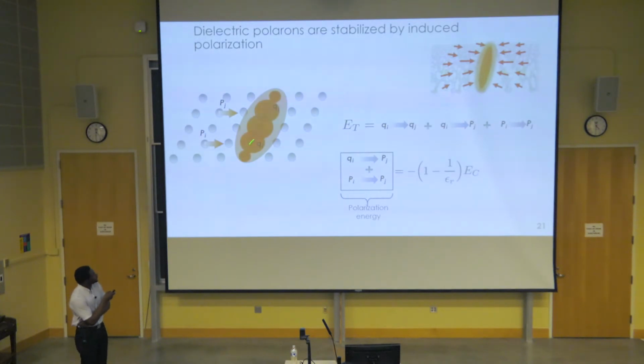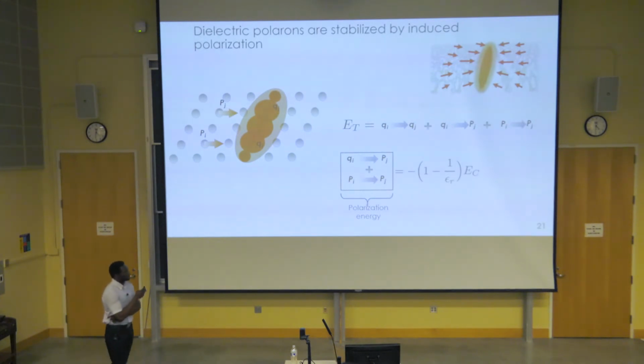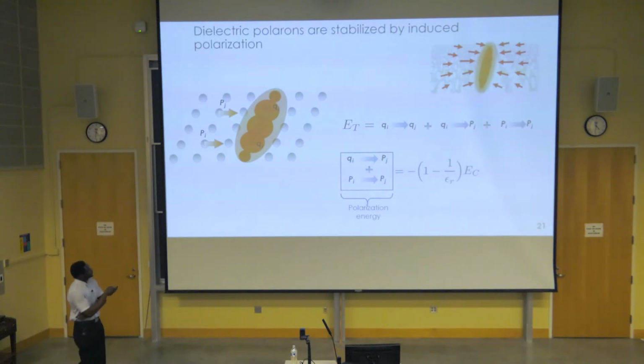And we consider the charge distribution as a superposition of local charges, much in the spirit of the tight binding approximation. And one can capture the energy of this system through a sum of pairwise interactions. So we have the charge interaction, charge-dipole interaction, and dipole-dipole interaction. It turns out that the energy that dictates the stabilization of the system is given by the polarization energy of the system, and that is because this charge distribution represents the quantum mechanics of a single particle which cannot interact with itself.